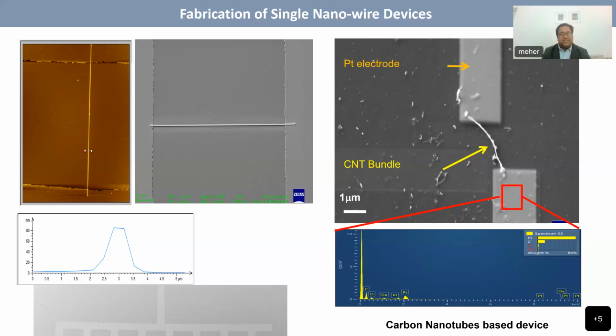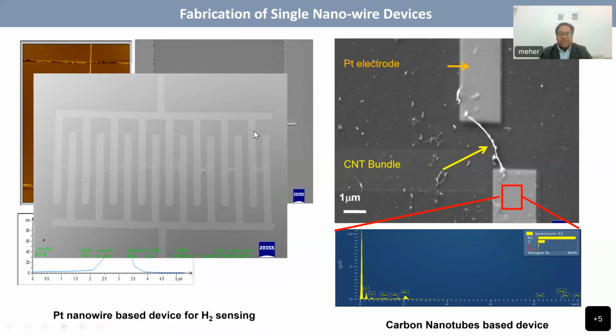So what I tried was, on an interdigitated electrode, I tried to put several platinum nanowires. You can see here, if you see carefully, there are many nanowires exactly put in line on the interdigitated electrode. It was a very tough task actually to pick a single nanowire and put it somewhere, because the nano scale is 1,000 times smaller than the micro scale. And if you talk about the micro scale also, the thickness of a human hair is generally around 200 to 300 microns.